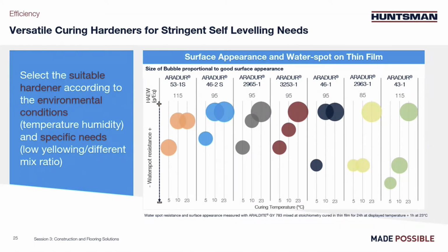To give a mark on those parameters, we have a scale for each test. We have run those tests in parallel, so the appreciation of the result is reliable. Based on the previous slides, the faster hardeners are on the left and the slowest on the right. You can immediately see that the Aradur 53-1S is very reactive, but is not the best for water spot resistance nor for surface appearance. Generally, for appearance, Aradur 46-2S gives the best result at all temperatures due to the good reactivity and best water spot resistance.